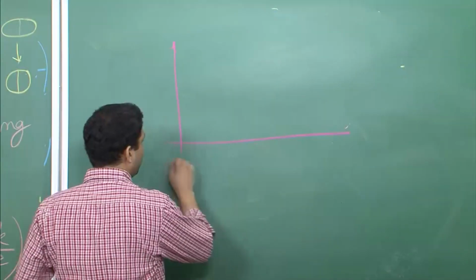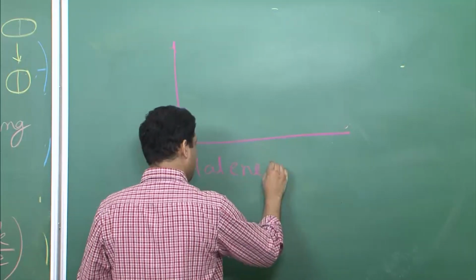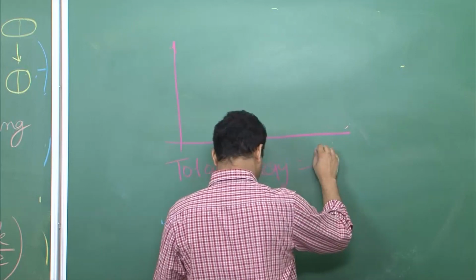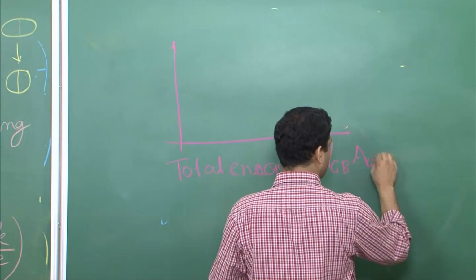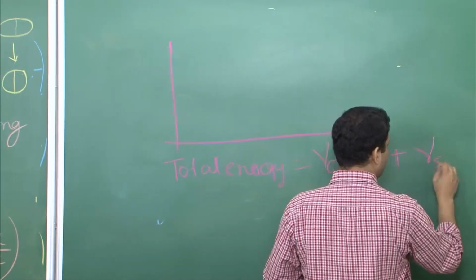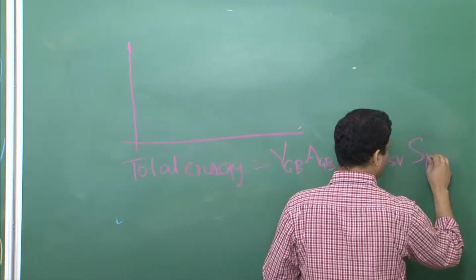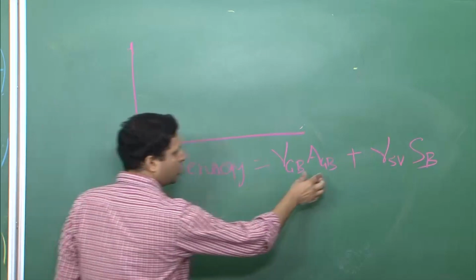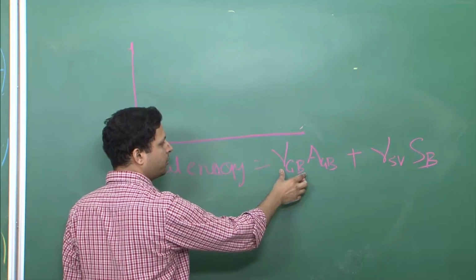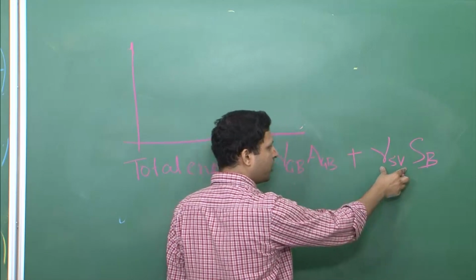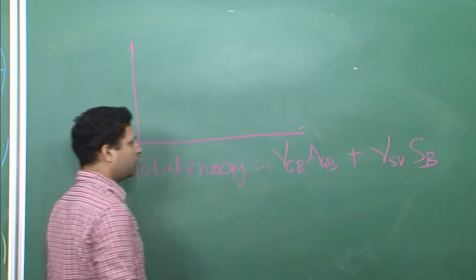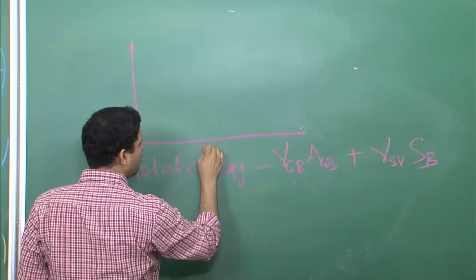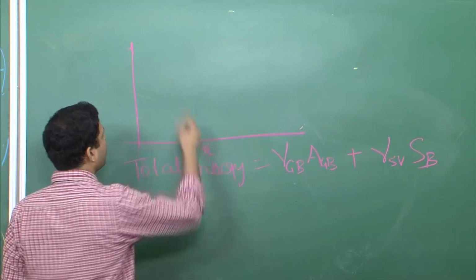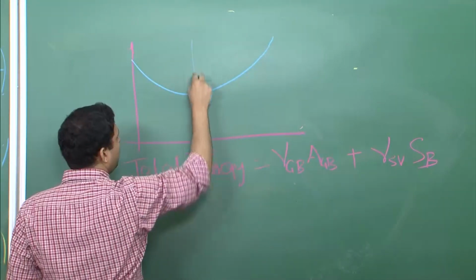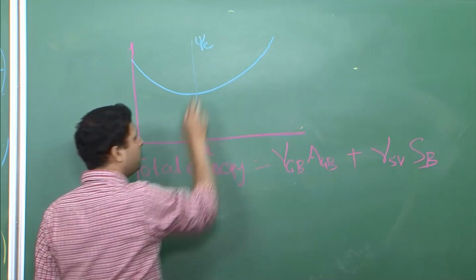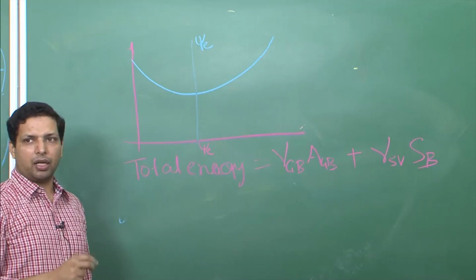so if we were to look at the total energy, we can write like this: gamma GB times area GB is for the two particulates. We are talking about gamma SV times surface of the particulates. So, this is the total area of grain boundary, and this is the grain boundary energy per unit area. So, this is the total energy. Similarly, this is the surface to volume energy per unit area, and this is the area of the surface. So, this will be the total energy, and if you were to plot this with psi c angle, you would get, so there will be a minima, and this is the psi E that will be your equilibrium psi. So, this is the angle at which it will become equilibrated.